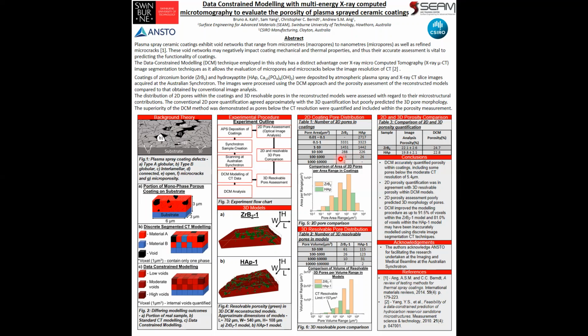The majority of the area corresponding to the 2D pores within the ZrB2 coating was found to be within the intermediate area range, as shown in Figure 5. Whilst the vast majority of the volume corresponding to the 3D resolvable pores within the ZrB2 model were within the largest pore volume range, as shown in Figure 6. This disparity is due to the fact that a 2D micrograph or model slice contains no information about the depth or 3D morphology of a void, or whether it is part of a strongly connected void network.